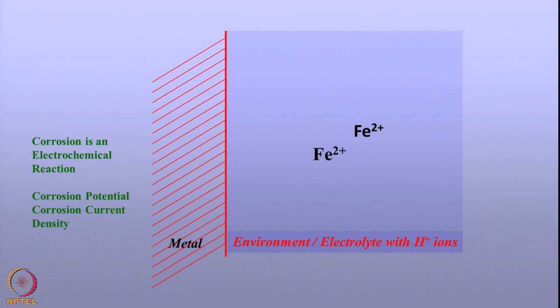Interesting to us is that suppose I immerse this metal surface in the acid and I use a reference electrode to measure the potentials, the metal will show a potential called the corrosion potential. In the cathodic protection parlance, we call them natural potentials, or it is also called open circuit potentials, because the current does not leave the metal surface. The oxidation reaction and the reduction reaction occur equally on the metal surface. There is a charge conservation taking place. So, if you look at the metal oxidation and use Faraday's law, then you can calculate the corrosion rate. The charges flown per second is related to the corrosion current density. In essence, aqueous corrosion, to be more precise, is electrochemical in nature.